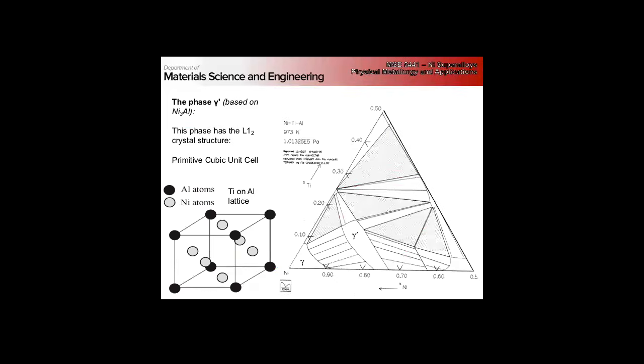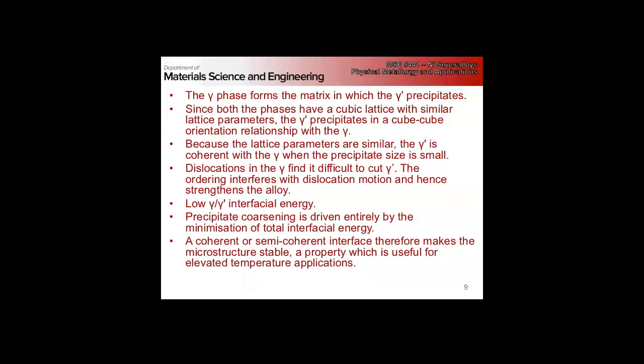Now, if the FCC 1/2 110 partials are separated into 2 Shockley partials, when they come through they form much more complex fault structures. So we basically have dislocations that want to stay together, pairs of dislocations that want to stay together, and chemical interactions with the dislocation, not only the typical shear stress. Okay, both phases have the cubic lattice with very similar lattice parameters.